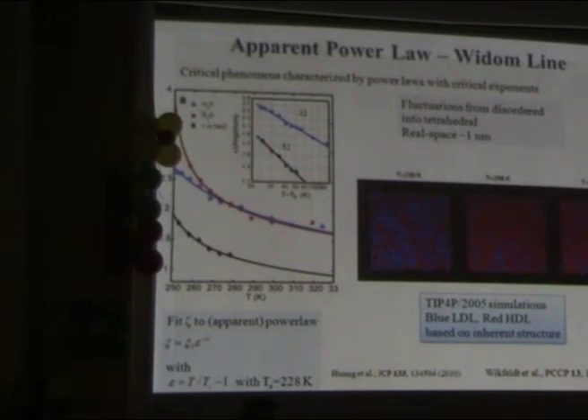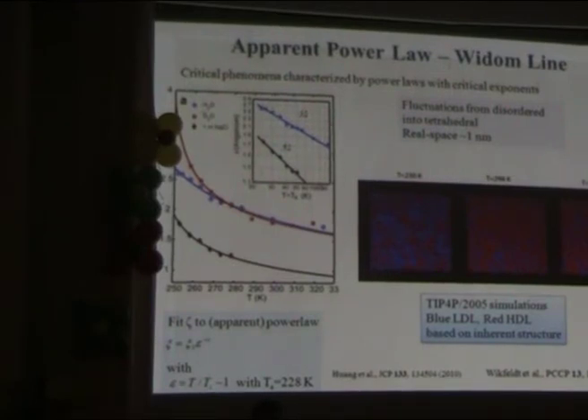So it seems that even in the correlation lengths we have a critical behavior. But also that for D2O we would be closer than for H2O. And the reason for this is that the hydrogen bond strength for D2O is enhanced over that of H2O. In fact, for a mixture of HDO and D2O, for instance, we see this experimentally from X-ray emission spectroscopy: we see HDO more preferentially in the high-density liquid rather than in the low-density liquid phase. And we can discuss that afterwards.